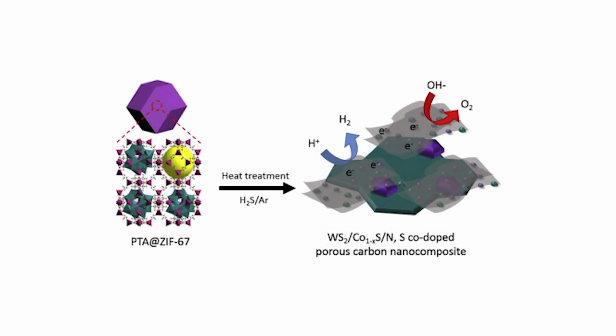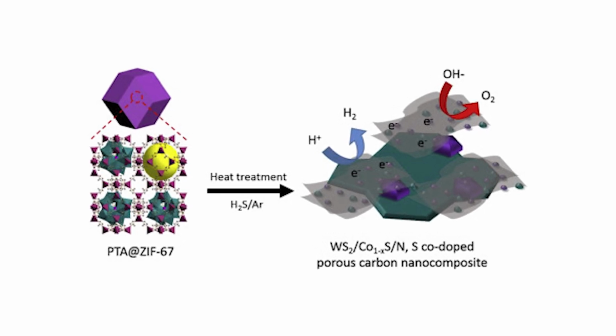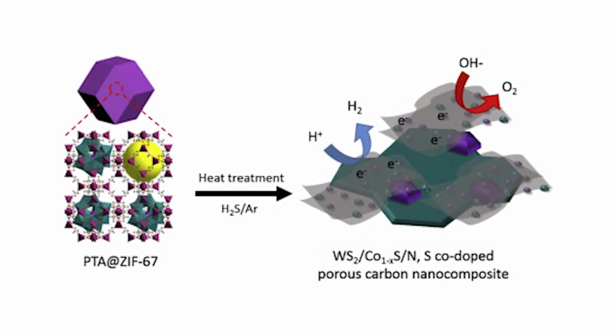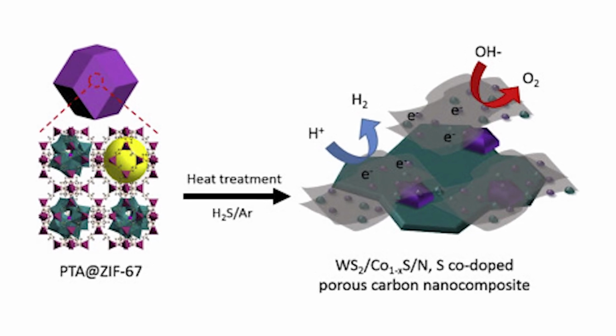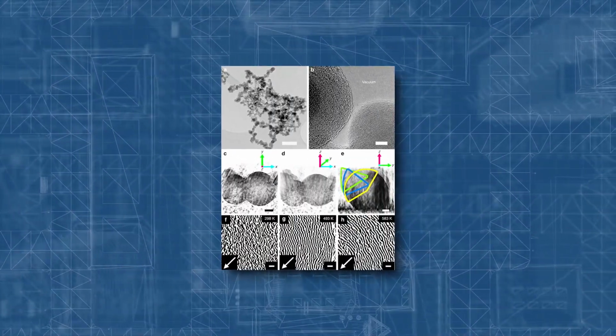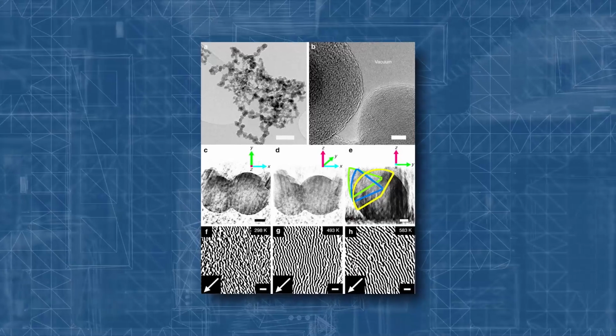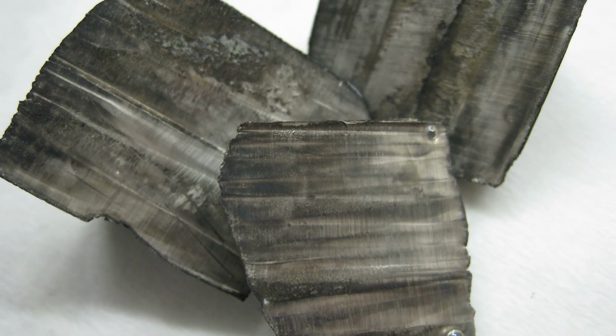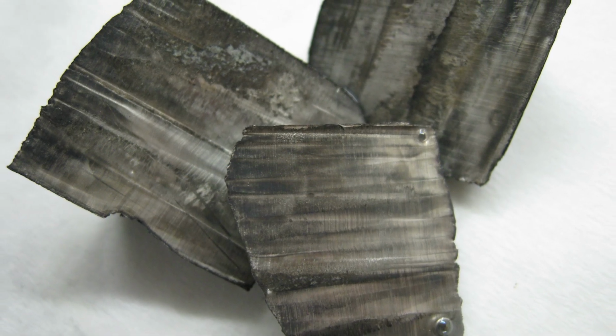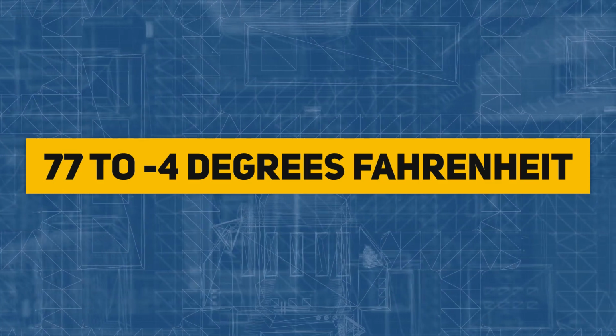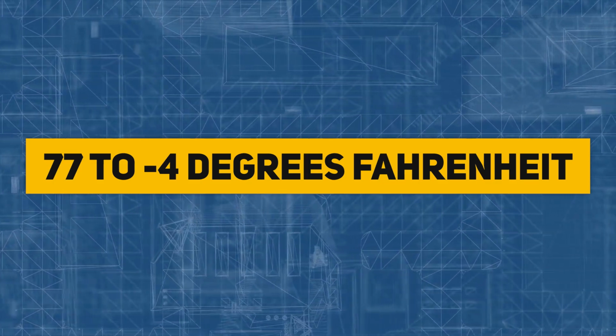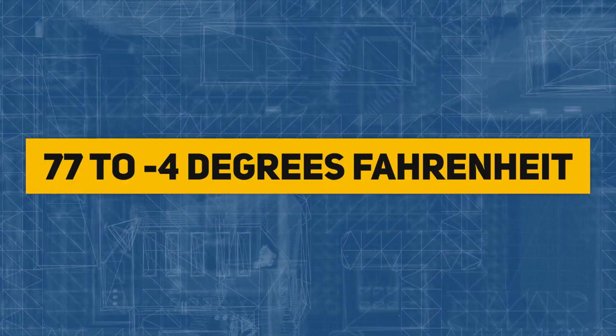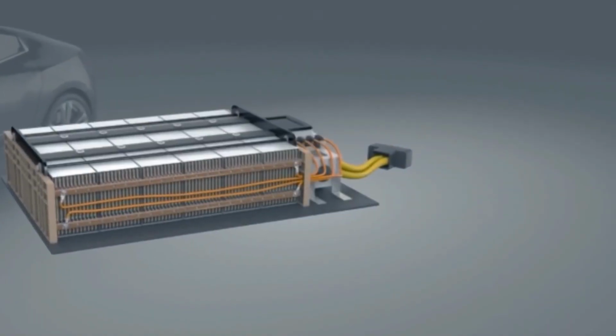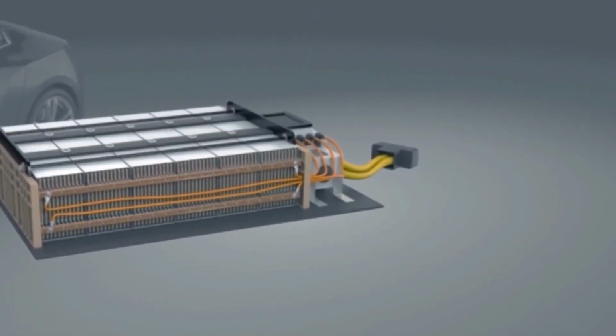Scientists created the novel material by heating the cobalt-rich zeolitic imidazolate framework, ZIF-67, at high temperatures. The rough surfaces of the 12-sided carbon nanospheres displayed efficient electrical charge transfer. The anode was tested using lithium metal as the cathode in a coin-shaped battery, and the results were positive. Temperatures ranging from 77 to negative 4 degrees Fahrenheit exhibited reliable charging and discharging of the anode, which held 85.9% of the room temperature energy capacity below freezing.